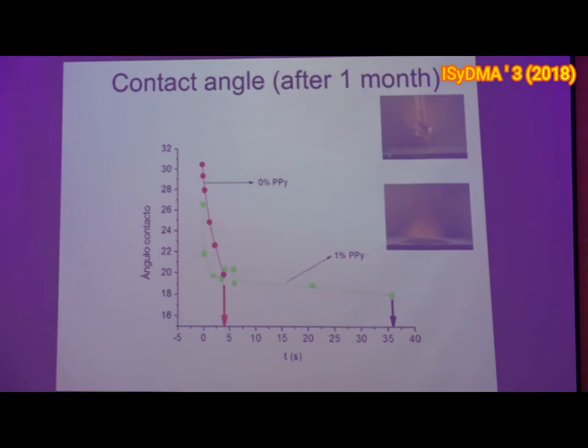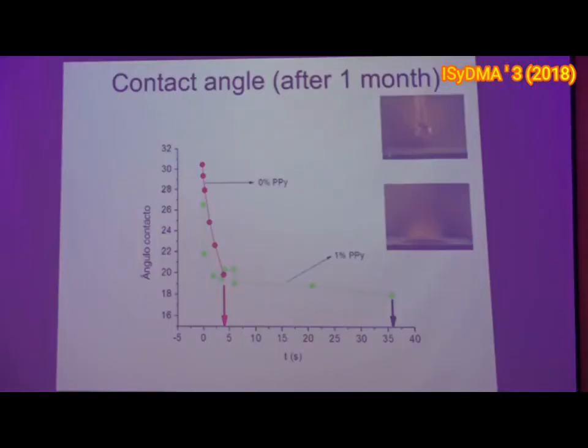And when we put only 1% of this conducting polymer, we can see it. So the curve is similar, but we must wait about 36 seconds to see the disappearing of this drop in the surface of the cement. So probably you can use this additive to improve the quality of the cement. Of course, the cement is a quite complicated material. We use pure cement, but in the construction they mix cement with rocks and sand, and so things are quite difficult. And probably the curves that we see, they are not so nice.